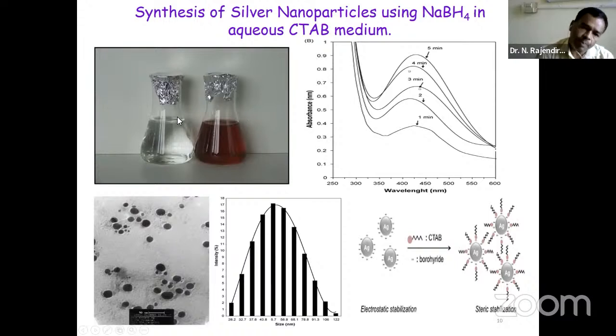And also during the preparation itself, we are able to confirm this. In this slide you see that the solution is initially colorless, whereas after the reduction, the solution exhibits an intense red color. So from this we can conclude the existence of silver nanoclusters. And further we can confirm by transmission electron microscope and DLS for the size and the shape.